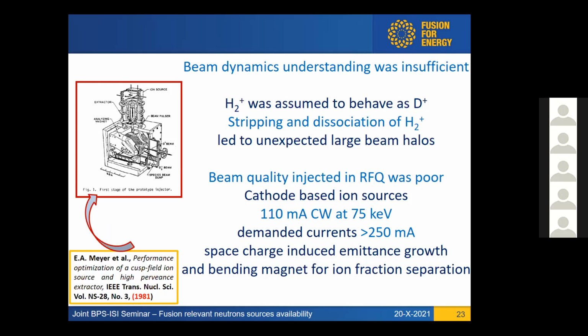They needed some bending magnet for ion fraction separation to make the distances longer, and these distances in accelerators, in what concerns the beam halo and the space charge phenomena, even 1 meter is something terrible, because the beam expands. So things need to be very, very narrow. So they basically didn't manage.